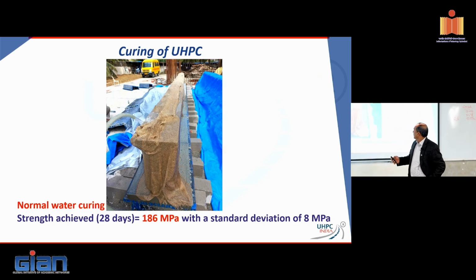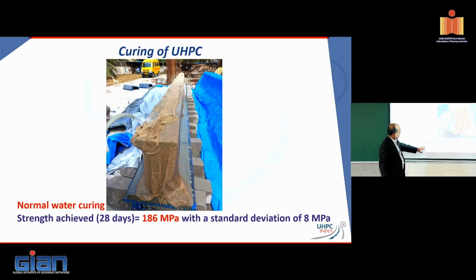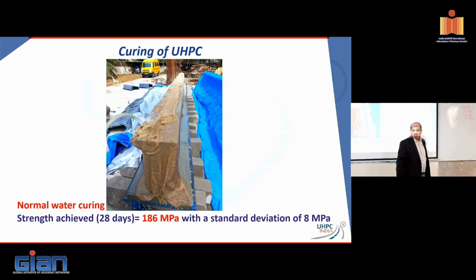Okay. But like I mentioned, you can do water curing. I'll tell you, this is with water curing. This is about 84 members cast over 30 days. The mean strength was about 186 MPa on site, with a standard deviation of about 8 MPa. That is what we achieved. Whenever you are measuring these strengths, are you using the standard cubes or 100 mm cubes? 100 mm cubes? Yes. Smaller cubes.